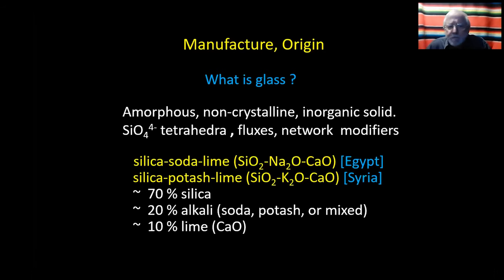This basic recipe that you're seeing does not take into account minor percentages of colorants, but they don't often affect the preservation or deterioration of the glass. Interestingly, this recipe though was what the Romans made, and it's actually what we still use today. It is the recipe for about 95% of all glasses.